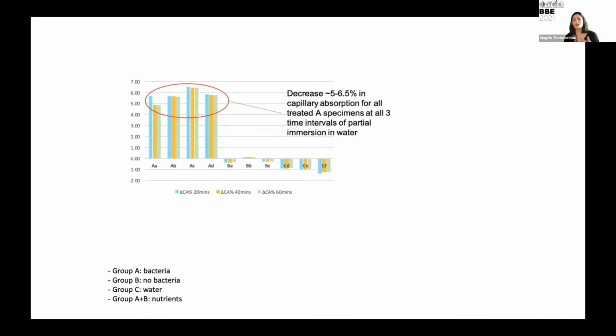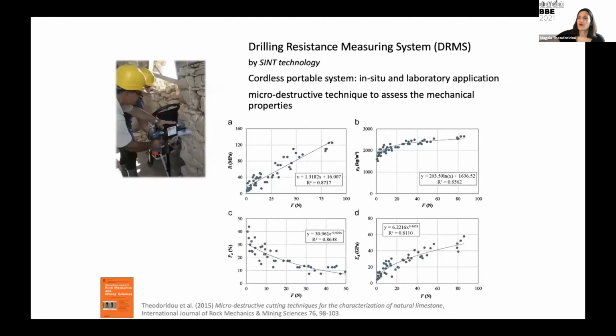And in this graph, you can see a group of specimens where we have a decrease in capillary absorption for all specimens that were treated with bacterial nutrients, while we see no significant changes in the specimens where only nutrients or only water was applied. And another method that we used, also to evaluate the changes of the microstructure, was a